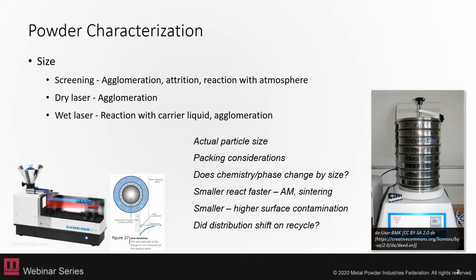But with screening, there can be effects like agglomeration of those powders, or you can break up some powders that have already agglomerated while you're screening. Also, those powders will be exposed to the atmosphere if you're screening within an air laboratory. And reactions can occur within those powders on their surfaces as you're going through the screening process. But you can also screen within a dry box or a glove box if you have powders that are sensitive to the atmosphere. There are other methods of screening, other methods of size classification and size distribution monitoring beyond screening.